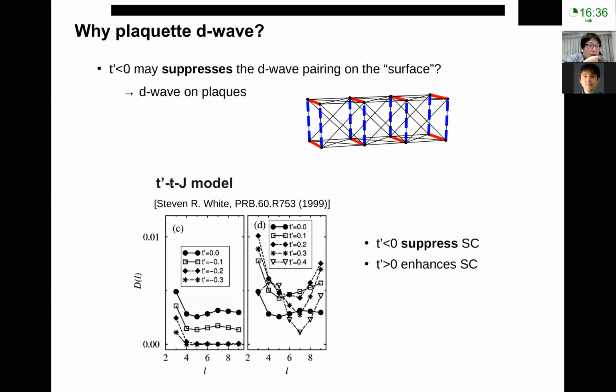So now the role of T-prime to superconductivity becomes a bit tricky, because in this 3D point of view, the T-prime cross hopping applies only on the surface of the cylinder. So it looks like you apply this T-prime on the surface, and then you push the superconductivity from the surface to the plaquette. This picture is consistent with the old study by Stephen White, who found in the TJ model that negative T-prime suppresses the superconductivity, while positive T-prime enhances the superconductivity.